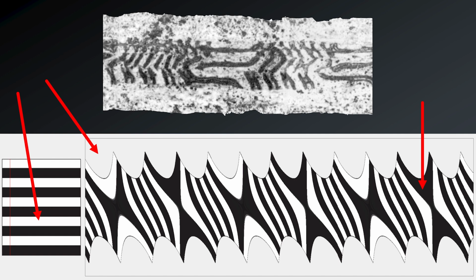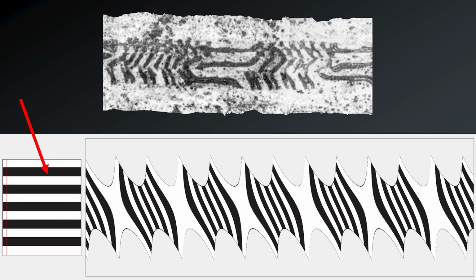This tells us that we should switch to a billet that starts and ends with white layers for the top and the bottom, like this one here. We have now gotten rid of the hourglass, and we have something that looks more like the original. But I have ended up with 5 slanted layers in our twist, and the original only has 3.